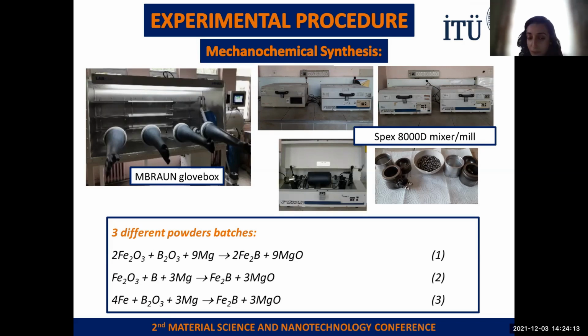Firstly, three different powder batches were prepared to synthesize the iron boride nanoparticles. The first one consists of iron oxide, boron oxide, and magnesium. The second one consists of iron oxide, boron, and magnesium. The third one, iron, boron oxide, and magnesium. We prepared the stoichiometric amounts. The powder batches are based on these raw materials.